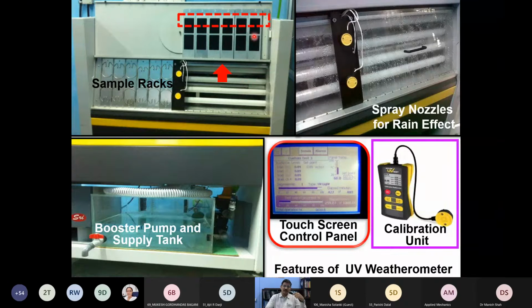These are the geomembrane coupons exposed to the UV light. In addition, in this system we have the possibility to spray the membrane to simulate rainwater. We can control the temperature. Humidity we cannot control, but we can control the temperature, simulate the rain effect, and change the intensity. In this particular case, I have set the intensity very close to 0.89 watts per meter square.